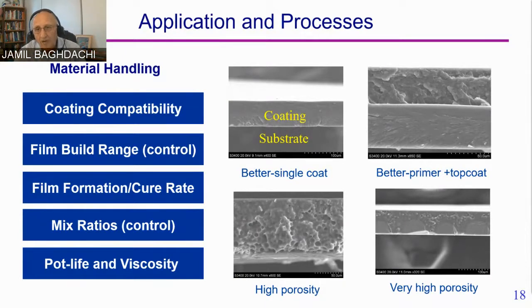I'm assuming on the right side, very high porosity. I don't know if you can see those things. Since you cannot see that, I made some marks in there for you to see. Click, please. If you click, there we go. Those are the areas that bubbles formed underneath. How about that? They put the paint in there, but because underneath there was oil apparently, or something was not really clean, the coating sat on it and cured or dried on it, but the holes were there. Imagine that if this airplane flies, water gets inside it eventually, not right away, right? Eventually it gets in there, and then expands, contracts, causes failure. Look at this. More than 50% of the area, as you can see, contains holes in it. Next, please.